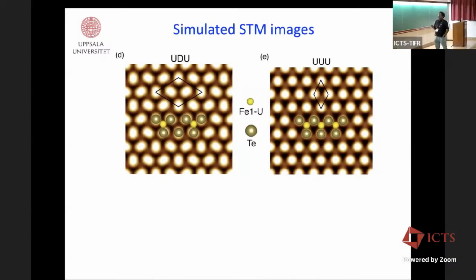Now, we have simulated STM images for these two structural models. If you look at the structure, you see that these white blobs here are not really circular. They are kind of oblate compared to the UUU structure. These states pop up because of the tellurium P states. The tellurium states are on the outermost layer. And you really see this non-circular shape for the UDU structure.